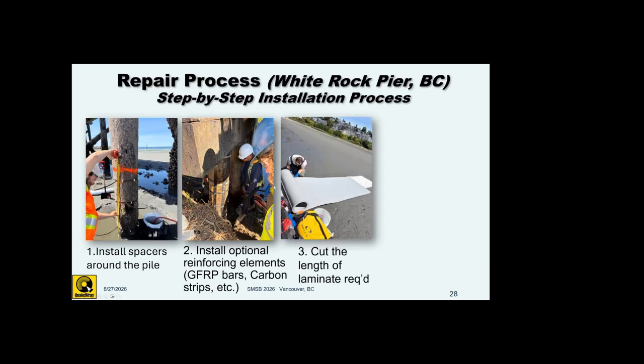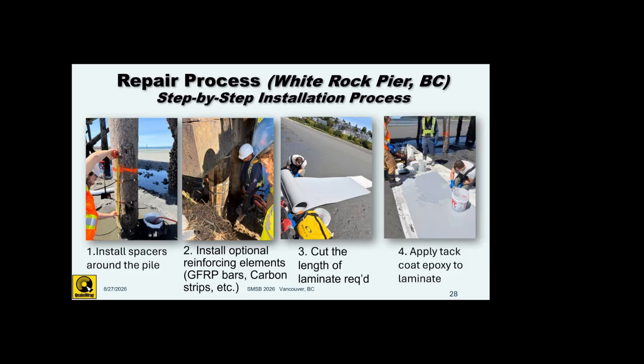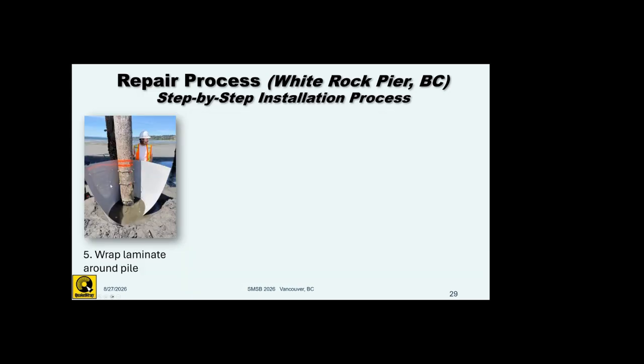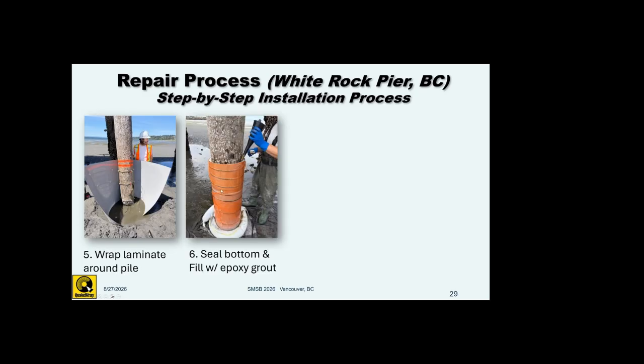Then you cut the length that you need from that fabric. Our typical detail is to go 2 complete turns and 8 inches. You apply epoxy on the second half of that cut length, and then wrap it around your column like twice and create a shell. You hold this shell together with ratchet strap or zip ties while the epoxy is curing. You can seal the bottom of it, and in this case we are filling the annular space with an epoxy grout.